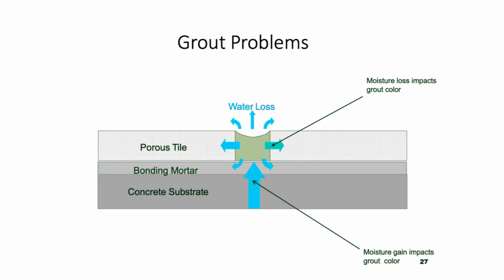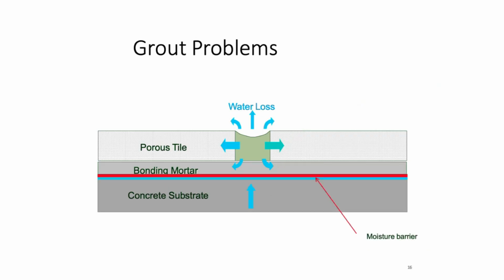Now you have a concrete substrate that you're going over with a mortar and no membrane. So let's say you've got a ceramic tile, you've got upwards, sideways, and down for your hydration process, nice and even. But now you're introducing moisture from the bottom. So that was another issue, that the moisture could get up through. I looked at a couple of jobs where the efflorescence was so thick you could break it off in chunks on the top of the tile. There's not enough grout in that grout joint to put out that much Portlandite or efflorescence. So it was moisture coming from the concrete substrate that was causing it.